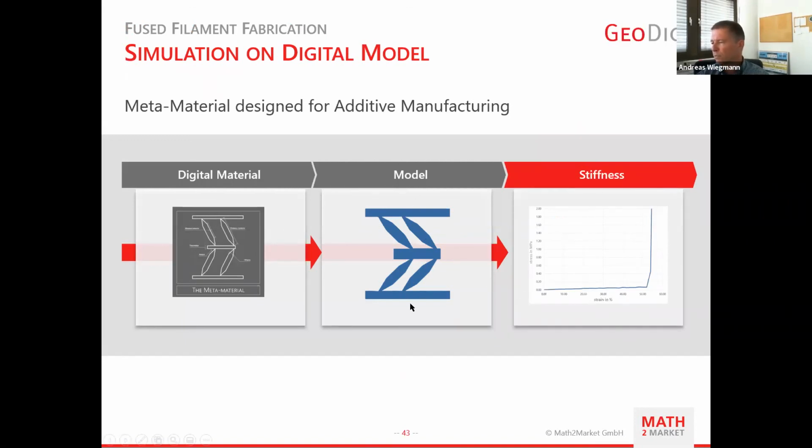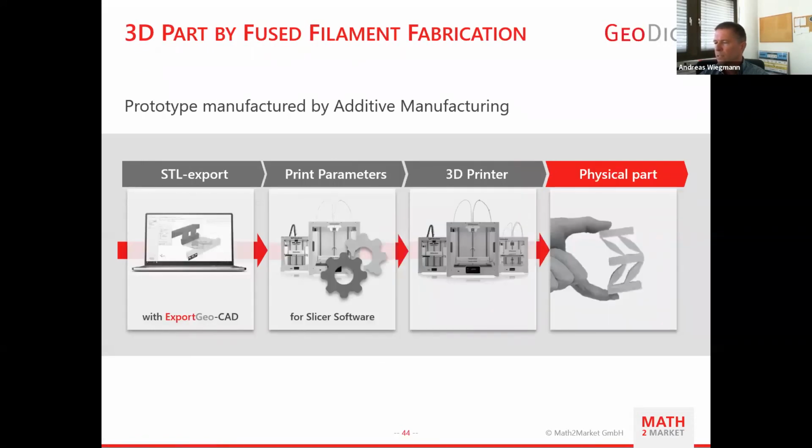So as you press on it from the top, initially there is very little stress in the objects until the thing has folded and the parts start touching each other, and then there's a very, very steep increase. And this was actually simulated on a CAD drawing, a 3D drawing of the thing, with our software that can also do mechanical simulations. So then the data were also given to a 3D printer. So that's symbolized here. And then that object actually existed in reality.